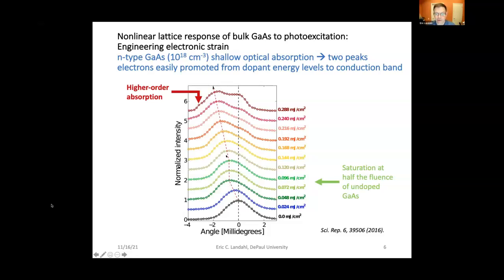And then again, with two-photon absorption onset, we see the expansion increase. And in fact, at high enough fluences, but still well below the damage threshold for gallium arsenide, one starts to see multiple orders come in. And these we interpret as being higher order photon absorption.